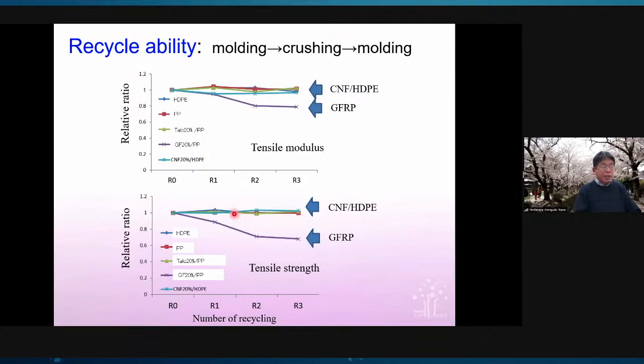Material recycling ability of CNF reinforced plastics should be noted. Because of the nanofiber reinforcement, CNF reinforced plastic is material recyclable. So crush and injection molding, and crush again, injection molding, and crush again, injection molding. We repeated material recycling, and the cellulose nanofiber reinforced high density polyethylene keeps the same tensile modulus and constant tensile strength. On the other hand, glass fiber reinforced plastics cannot.